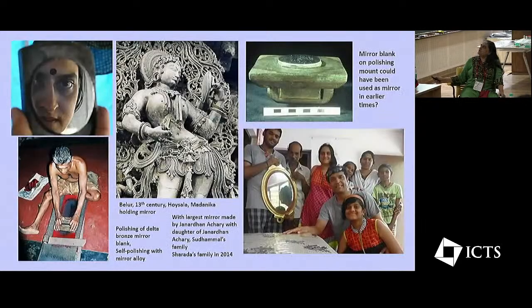And then the next process, of course, is the polishing of that blank. You're seeing here that after it's cast, it looks like that. Sometimes it can have some defects. Then it's mounted onto this wooden polishing mold, and it is lapped here for several days back and forth. I don't know if you all have worked with metallographic polishing, but you would remember the rule that you first get all the scratches to go in one direction, and then you look at it under the microscope. When it's all in one direction, then you go the other direction. They do something similar, though of course they are able to observe it just by watching, by visual observation, maybe because these are very large crystals we're talking about.